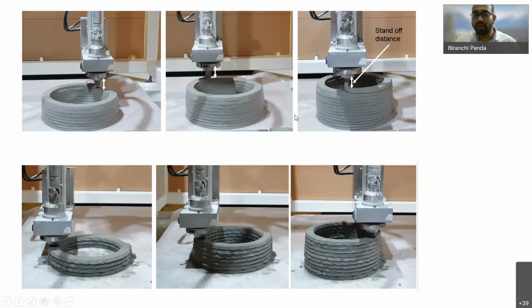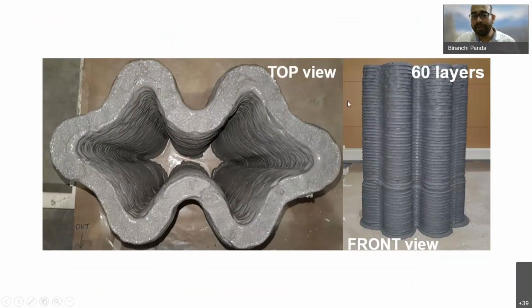So you may go either for a rheological test. Sometimes students try to do some kind of test to find whether the material is slumping. In civil science, we call it slumping behavior. So if the material is slumping during the printing process, you will get this kind of stand off distance increasing. But if there is no slumping, the material is very stiff and accurately deposited, you won't find any significant difference. So this is how two materials behave completely differently from a concrete printing point of view. With this printing process, we are able to print 60 or more than 80 layers without any deformation.